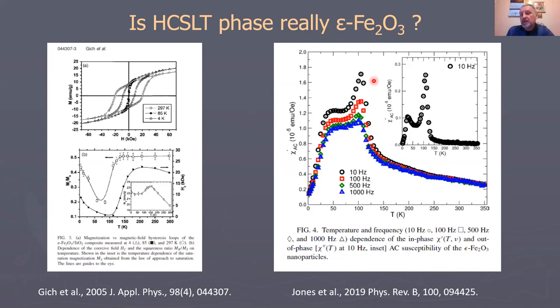The susceptibility versus temperature on a 10 nanometer sample behaves also in a quite interesting way, and that temperature dependence could probably serve as a discriminant for that phase where it's observed in natural samples.